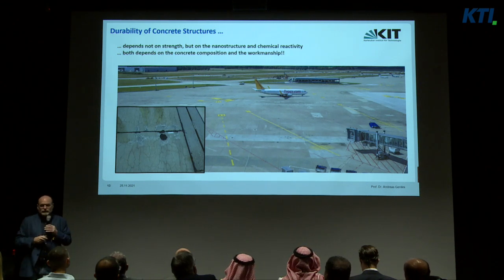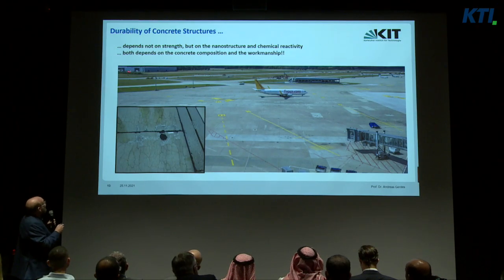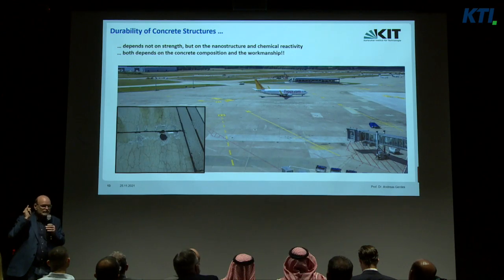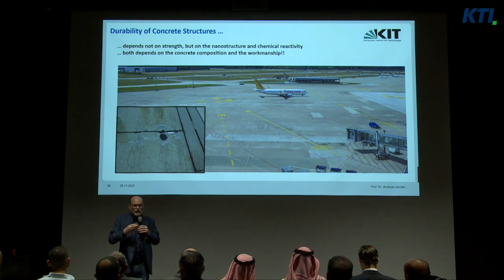And this depends not on the strength. It depends on the nanostructure and chemical reactivity of our hardened cement paste. And both depend on the concrete composition and, this is the most important point, on the workmanship. Because if you prepare the perfect concrete, but there's nobody on the construction site who can apply this material in the right way, then of course the best concrete in the world doesn't work. So therefore it's necessary not only to control the concrete, but also to control the ready construction, making a quality control. Please remember, we are sometimes paying millions of dollars for one construction.